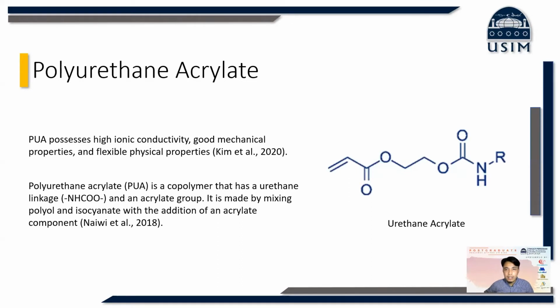Polyurethane acrylate, the polymer matrix used in this research, possesses high ionic conductivity, good mechanical properties, and flexible physical properties. Polyurethane acrylate is a copolymer that has a urethane linkage and an acrylate group. It is made by mixing polyol and isocyanate followed by the addition of an acrylate component.